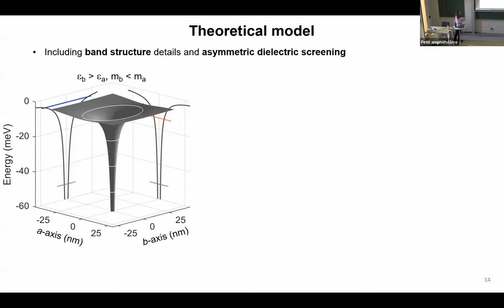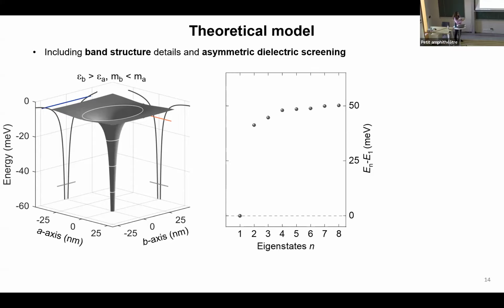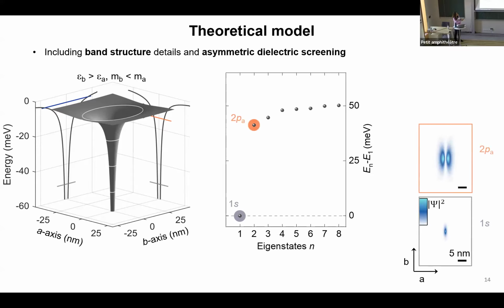And the excitons inside this potential will have quantized energy states, and we can nicely recognize the 1s orbital, 2pA orbital, and 2pB orbital through the form of their wave functions. What is interesting is that the 1s orbital is really localized and slightly dispersed along the B direction. However, when we take a look at the shape of the 2p orbitals, we see that the 2pA orbital is very squeezed spatially. However, the excitons in the 2pB orbital are highly dispersed along the B direction. So already their wave function behaves pretty much like a quasi one-dimensional wave function. And that explains why the excitons acquire this quasi one-dimensional behavior in chromium sulfide bromide.